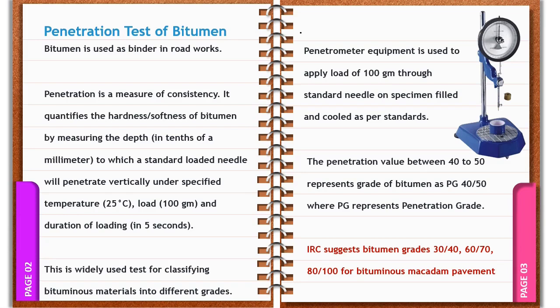For example, if a given sample has a penetration value of 44, that means it has penetrated to a depth of 4.4 mm. Since the scale on the equipment is in terms of 1/10th of a millimeter, 4.4 mm is translated to a reading of 44. Since this penetration value lies in the range of 40 to 50, the given sample will be assigned a penetration grade of 40/50. The Indian Road Congress suggests bitumen grades as 30-40, 60-70, and 80-100.